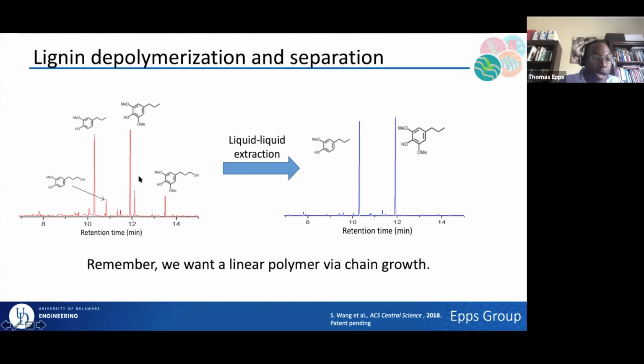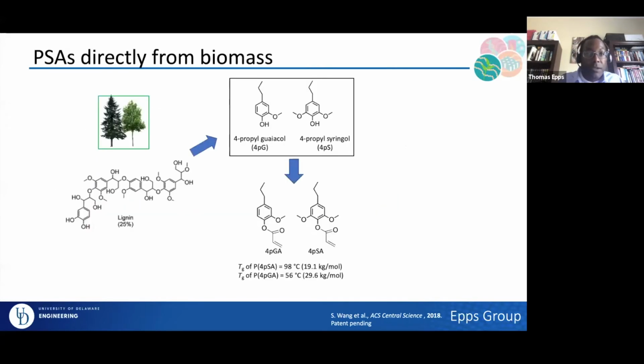We want to have a linear polymer, and you'll notice, for example, these dihydroxyl species here and here. So the nice part is the only separation that we had to do was a liquid-liquid extraction with a hexane, water, a little bit of methanol mixture, and we're actually able to end up with a gas chromatogram that looks like this, that only has these monofunctional species that then we can functionalize to make our chain growth polymer. So no column chromatography or anything for these bio-based feedstocks.